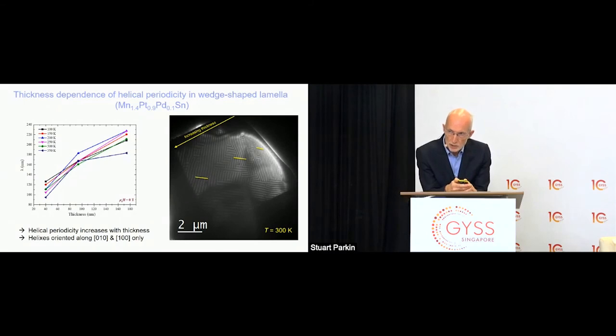And you can see as we go from the right to the left in this lamella, the thickness of the lamella was designed to increase. And you can see that the spacing of these white lines increases, and it turns out the period of this helix increases monotonically with thickness.